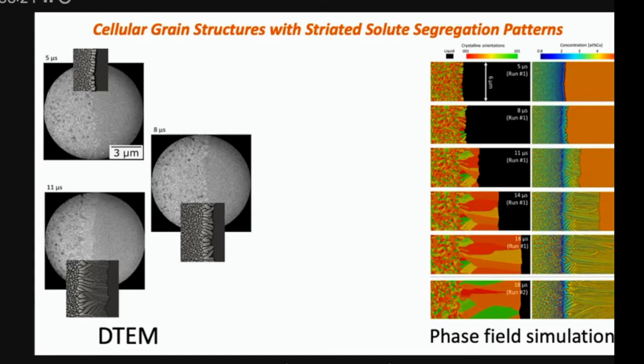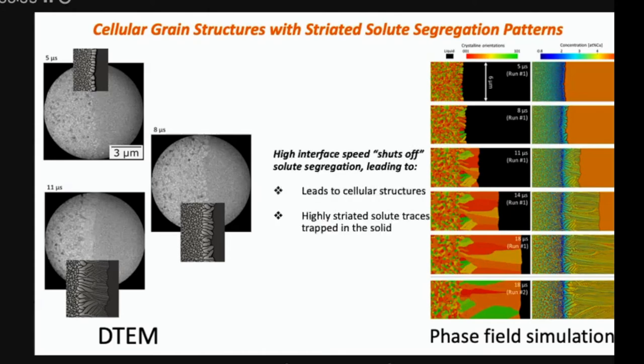And here's another view of the same thing, showing our simulations. On the left, the colors represent orientation of grains. On the right is concentration. What's very interesting and similar to the experiments is you see initially you have a bunch of disconnected grains that started to grow, but they very quickly joined to form almost a continuous, very gradually wiggly front of interlocking grains of different disorientations. But if you look at the concentration, it tells a more interesting story. Within a given grain, you see that there are many striated channels of solute.